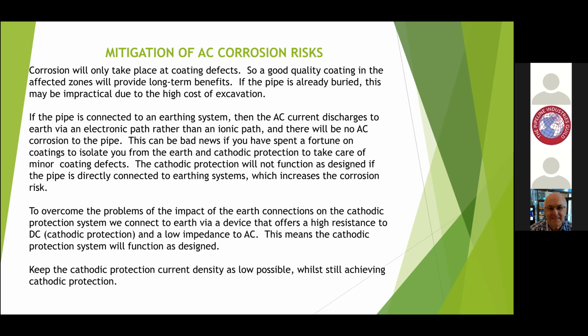Well, the first thing to bear in mind is that corrosion only takes place on the pipe where the bare steel is exposed to the electrolyte, whether that electrolyte happens to be concrete, water, soil. And I haven't discussed in this presentation the corrosion risks that exist on steel reinforcement in concrete, in tunnels and crossings and so on, because this is just related to pipelines, but the same risks are there. So it's not too hard to understand that if you want to get rid of the AC corrosion risk, you need to get rid of the AC, because without the AC, you haven't got a problem. And the reason that the AC is induced in your pipe and it leaves the pipe is because it wants to get back to where it came from. So if you can remove the AC, then you won't have an AC corrosion risk.